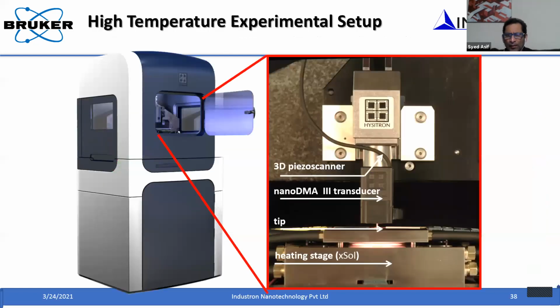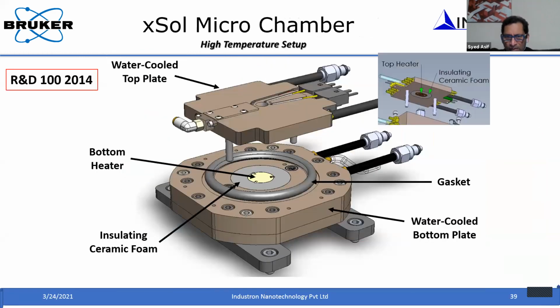Again, I'm going to speed it up. You can do these experiments as a function of temperature using this xSol heating stage. This is the xSol heating stage that we typically use. This stage has been designed to eliminate drift. We can sandwich a sample between the top heater and the bottom heater. When they are sandwiched, you have a gasket, and you create a small space between the top and the bottom heater. Within that space, you can control the atmosphere. You can put an inert gas, or you can have, for example, cold nitrogen or humid air. So you can have different atmospheres, whatever way you want, in that micro chamber. And then you can do the experiment, and you can do this mapping experiment that I just presented.